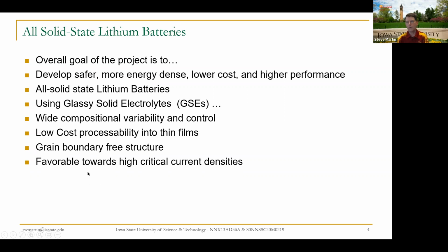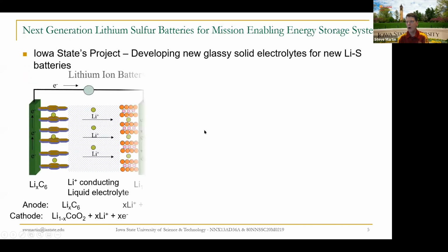In the interest of time, I won't go into all that, but suffice it to say, our project then is to replace these carbonaceous cobalt lithium ion batteries where the separator is a piece of plastic filled with liquid. And here you can see the cartoon showing how many carbon atoms it takes to store one lithium ion. So that's why they have low energy density. It just takes so much carbon, 6 to 1. Cobalt's a little better, 3 to 1, but you can't take all the cobalt out. X is about 0.5. So it's 0.5 to 3 or 1 to 6.